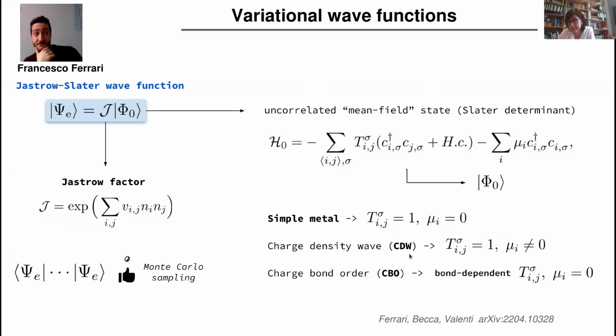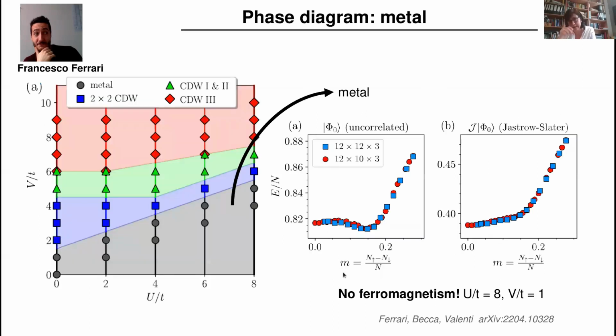So either you have a charge density wave or a charge bond order, and there's a lot of variability in getting these phases. Now what's interesting is this phase diagram: on-site Coulomb repulsion as a function of nearest-neighbor Coulomb repulsion. What one observes is the following: if we don't have the Jastrow factor, so at the mean-field level, in the region where the other calculations were getting ferromagnetism, ferromagnetism wins at the mean-field level. But as soon as you include more correlations, this phase is washed out—we know correlations tend to wash out phases predicted by, for instance, Hartree-Fock. So in fact, this becomes a metallic phase.